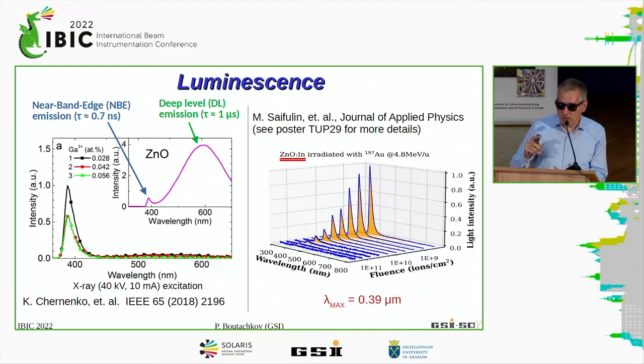And now I want to show you the response to heavy ions. So the picture to the left was excited with X-rays. To the right, now we are exciting with heavy ions, relativistic ions. Now, just a few important features here. As we are increasing the flux, which is on one of the axes, we're damaging the material. The light coming from the fast decay is reducing, but the green band does not come back, so it is staying a fast scintillator, a bit, as we are damaging, even at quite high fluxes.